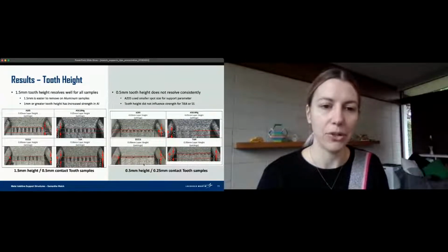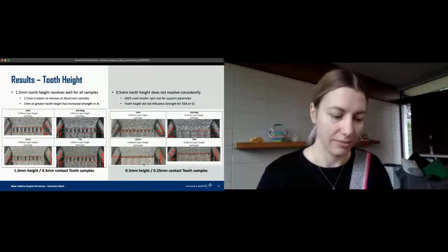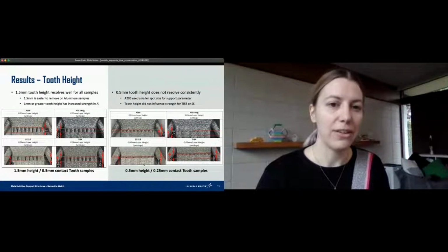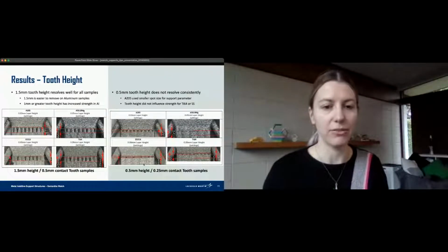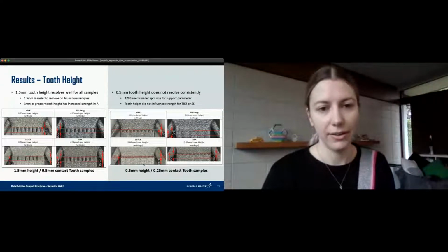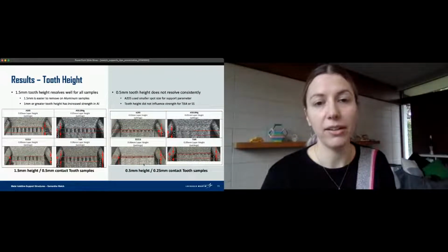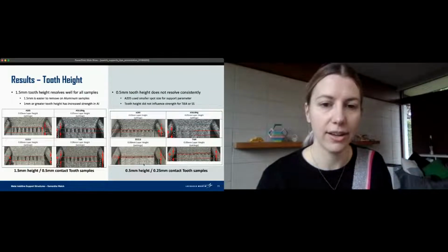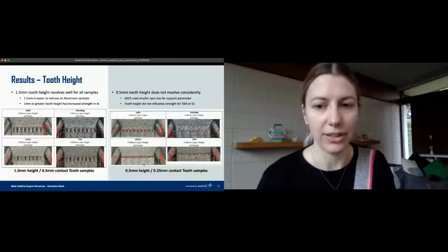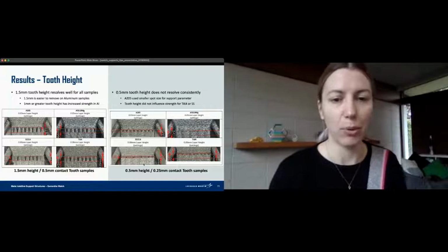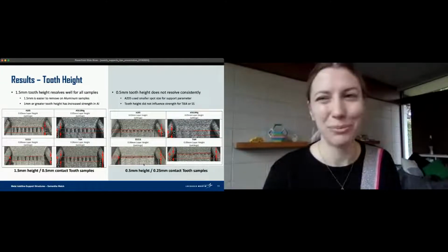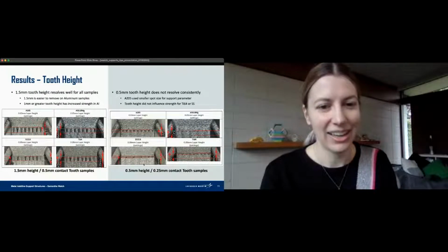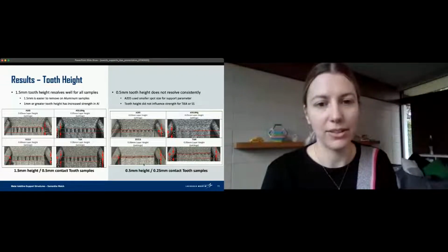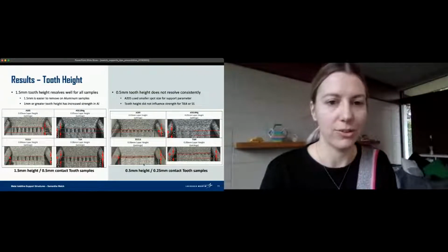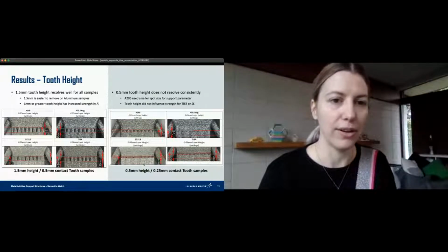But as we're scaling up to higher power laser settings and larger platforms, our small features don't quite resolve in the same way unless we're specifically optimizing for that. And so the larger teeth were able to resolve more repeatedly across these various settings and platforms than the smaller teeth, which gave us a more robust, repeatable result, which is what you want when you're printing fairly critical parts. I also found that for the aluminum parts, this correlated with a minor improvement in strength. The larger teeth were easier to remove and were slightly stronger.